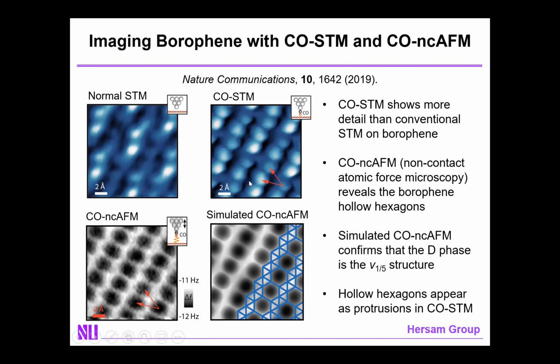But even more compellingly, if you move into non-contact AFM mode, which is less sensitive to electronic structure than STM, you now see in real space these hollow hexagon structures that we deduce from X-ray photoelectron spectroscopy. And if you simulate, in this case, the V1/5 structure, you see very nice agreement with experiment.